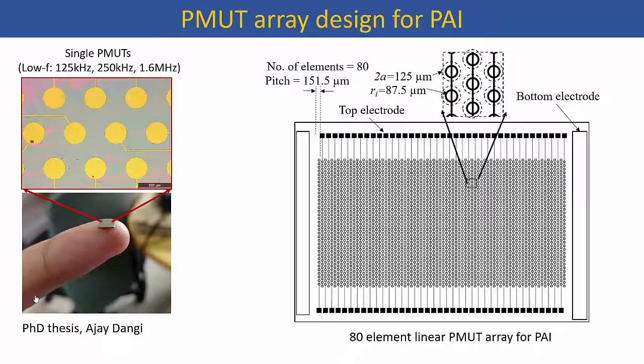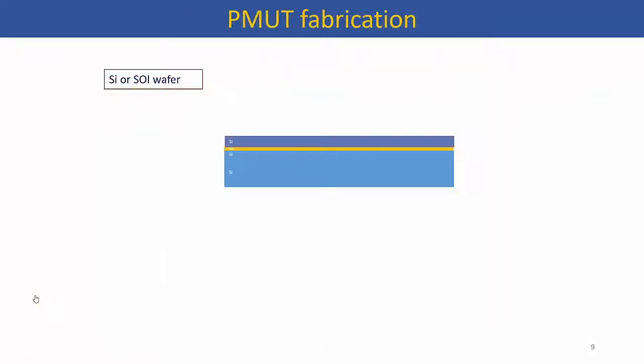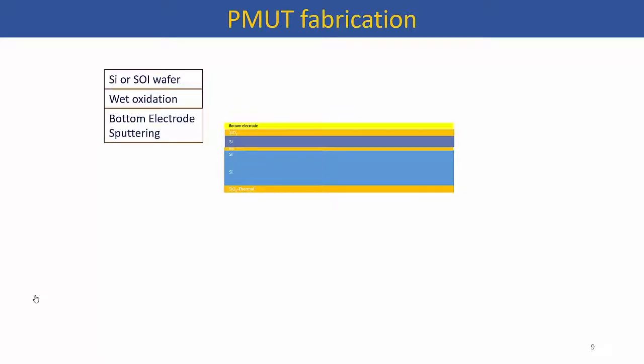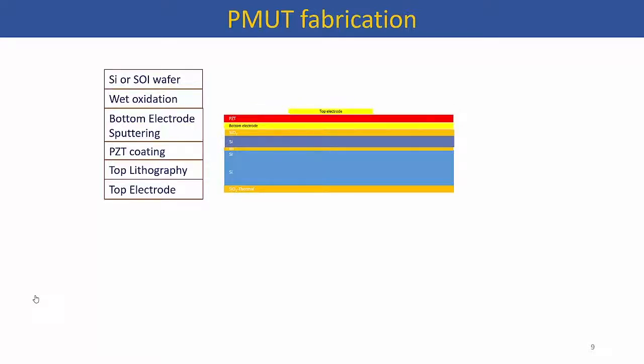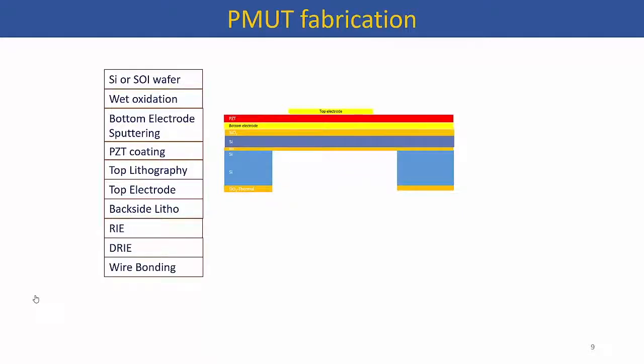Earlier in my PhD I was working with low-frequency PMUTs, but for this work we targeted the highest frequency we have been able to achieve so far. The fabrication process starts with a silicon wafer — you first deposit SiO2 on both sides, then put down the bottom electrode, which is platinum with a titanium adhesion layer. Then you deposit PZT, which is a very challenging task done here by sol-gel coating. After multiple iterations we reach the target thickness. After that, we do top lithography to pattern and deposit top electrodes, so you have electrodes on both top and bottom to apply voltage across the PZT layer. Finally, we define a window on the back side and use DRIE to remove the handle part of the wafer, leaving behind a membrane to vibrate.